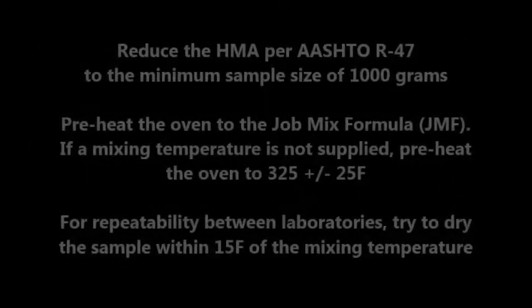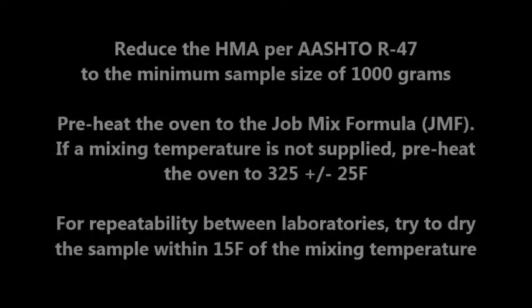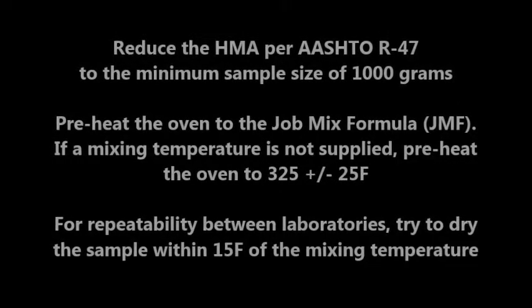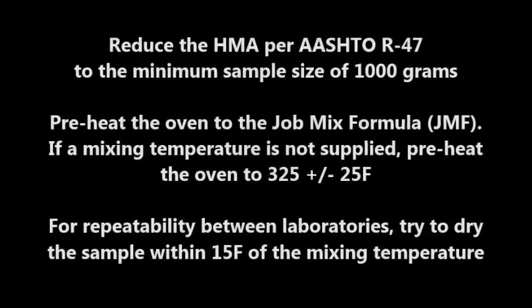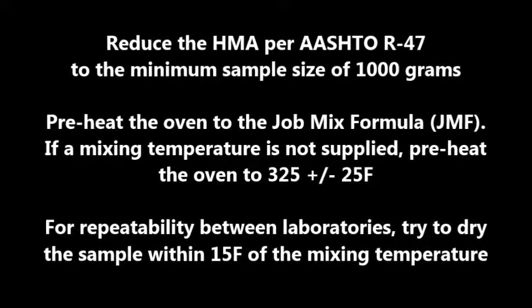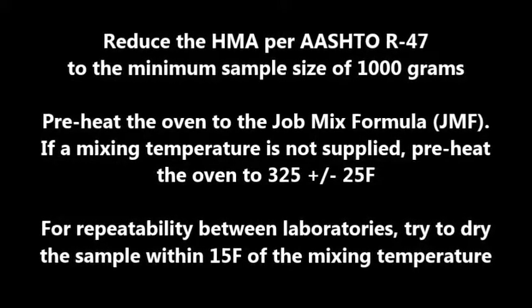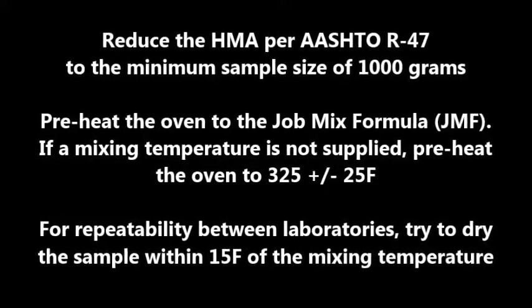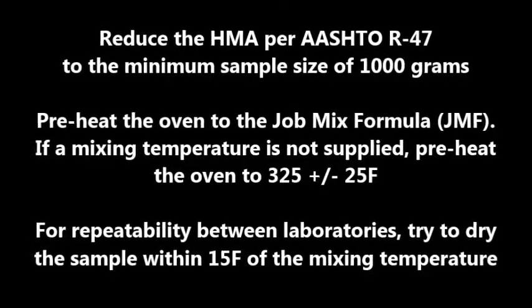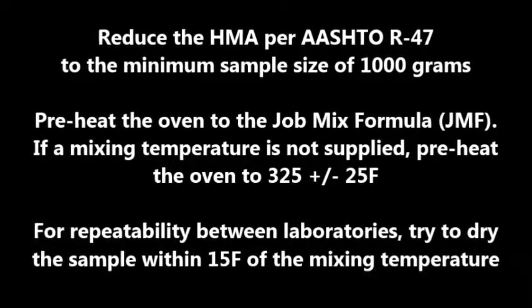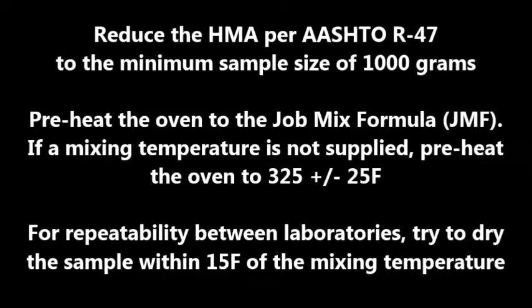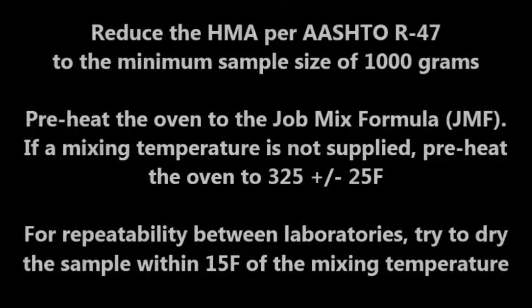Reduce the hot mix asphalt per AASHTO R47 to the minimum sample size of 1000 grams. Preheat the oven to the job mix formula temperature. If a mixing temperature is not supplied, preheat the oven to 325 ± 25 degrees Fahrenheit. For repeatability between laboratories, try to dry the sample within 15 degrees of the mixing temperature.